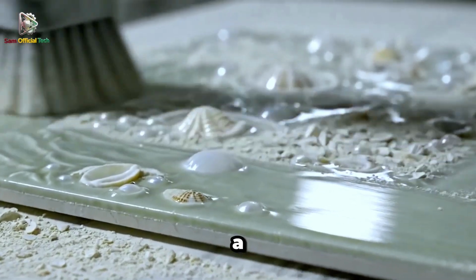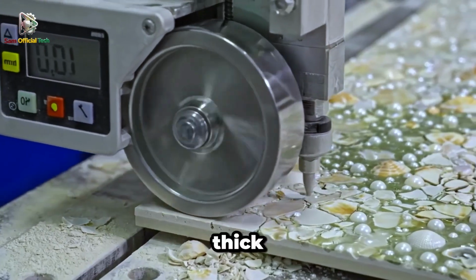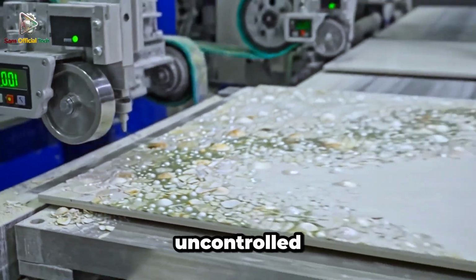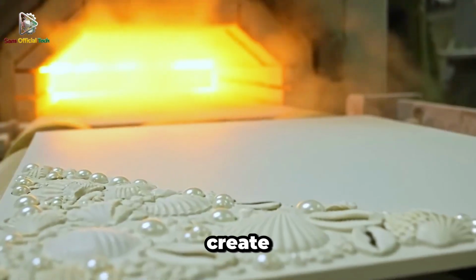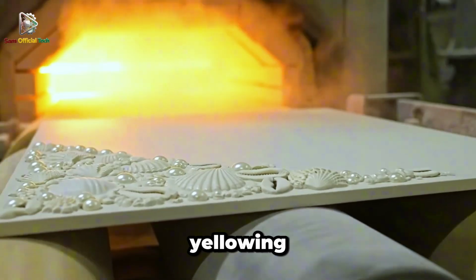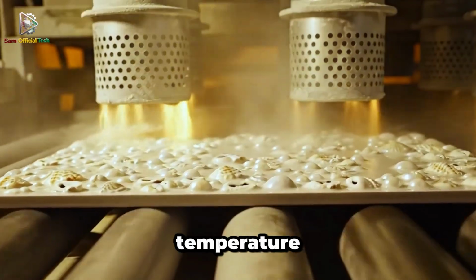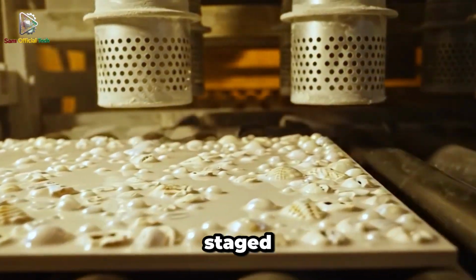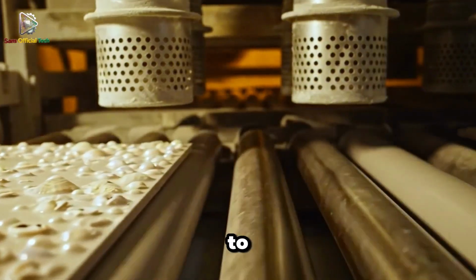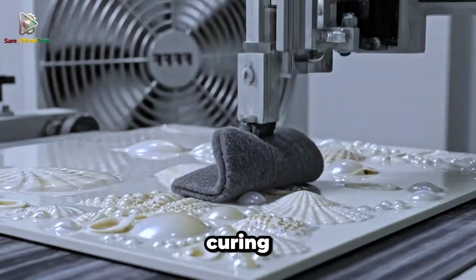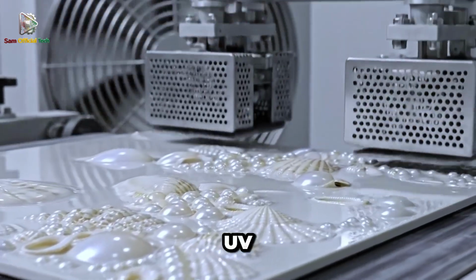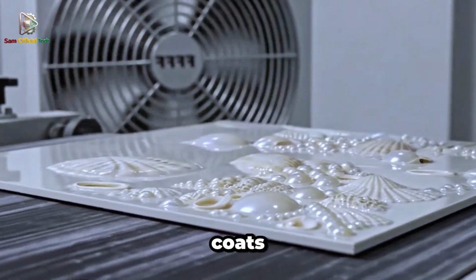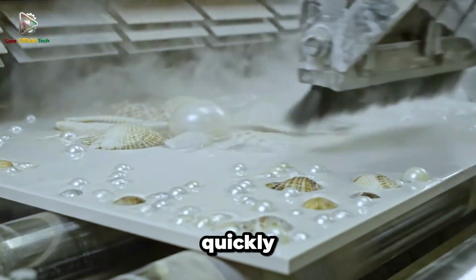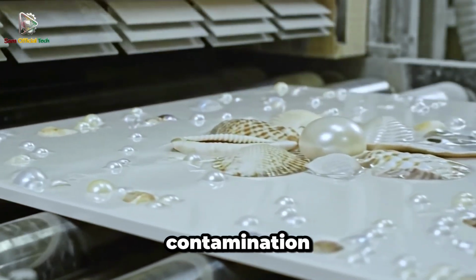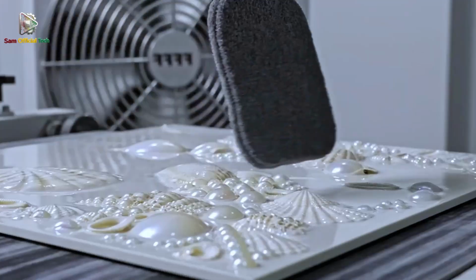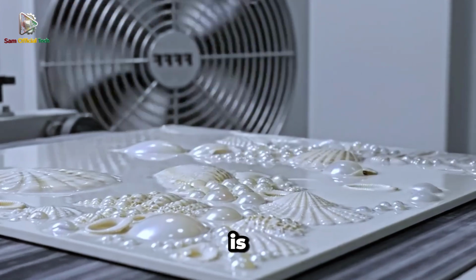Curing is treated like a controlled chemical reaction. Thick resin pours generate heat, and uncontrolled heat can warp substrates, create microcracks, or cause yellowing. High-tech plants cure in temperature-controlled rooms and may use staged cures: a slower initial cure to reduce exotherm, followed by post-curing to maximize hardness. UV curing may be used for thin top coats because UV systems can lock a surface quickly, reducing dust contamination and increasing throughput.